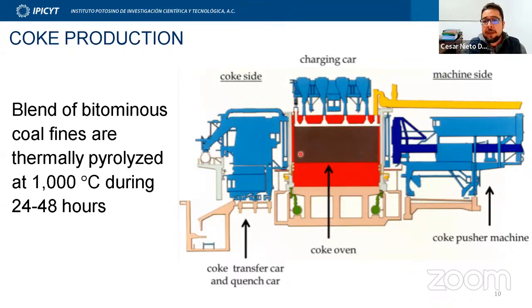The production of coke essentially is the pyrolysis of bituminous coal, and during this process, the coal powder gets melted, and also all the volatile bits just get released. And because it's a pyrolysis process, you need to keep air outside of the oven, and also the consumption of energy is very high. This is the main chamber. Here, I will show you the burners in the next slide, but here is the charging car.